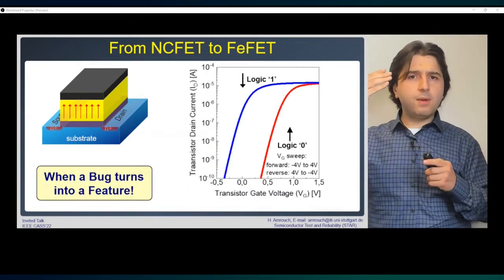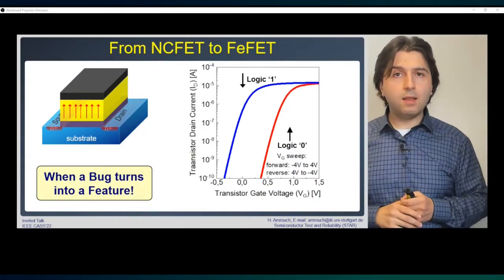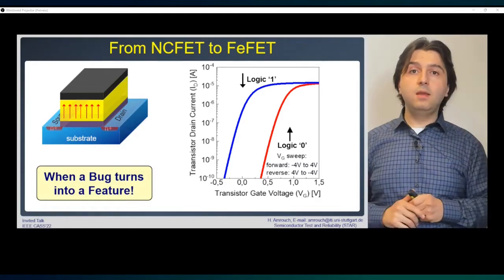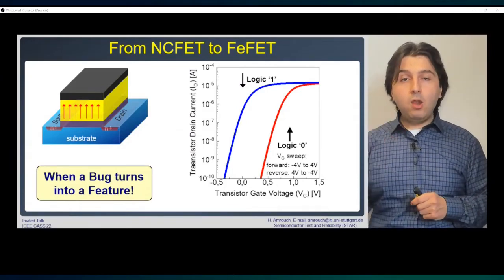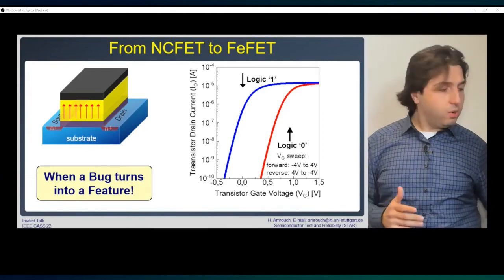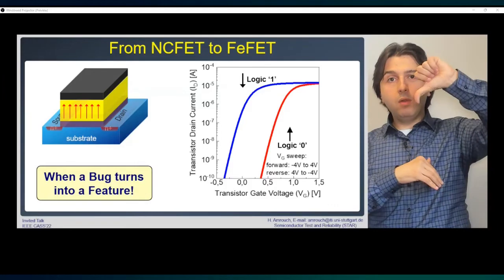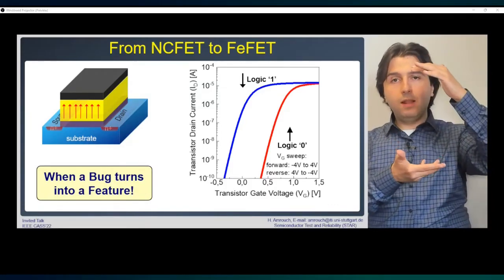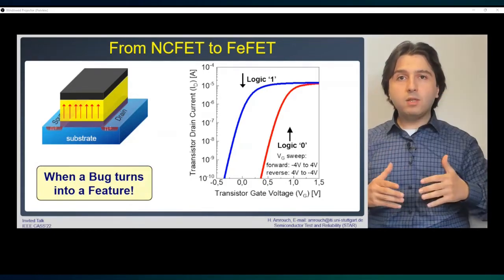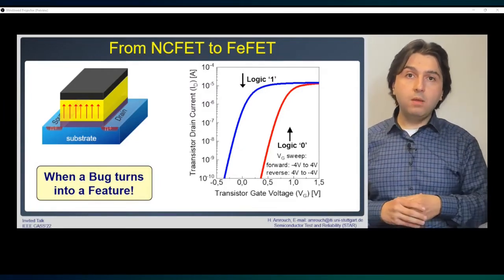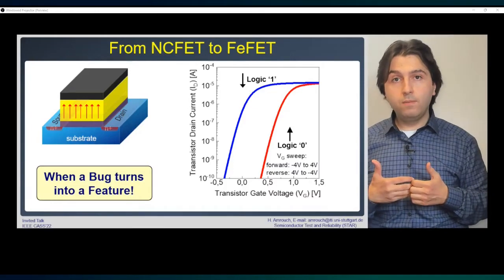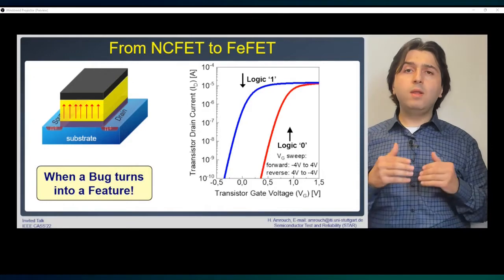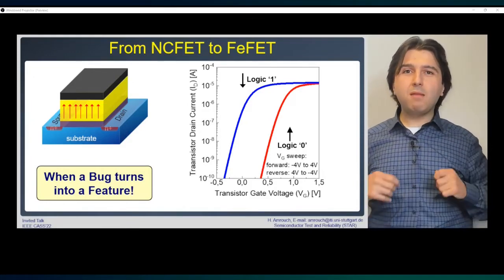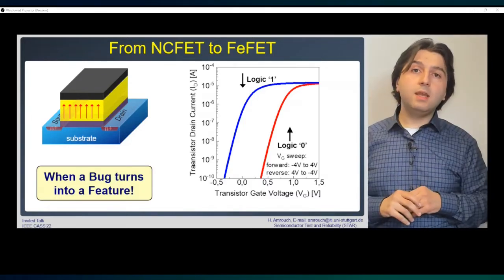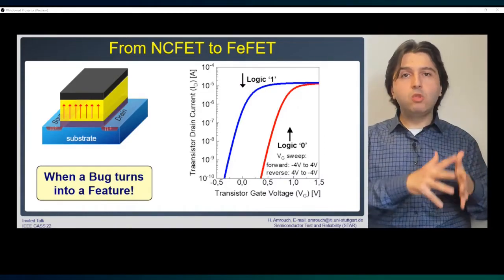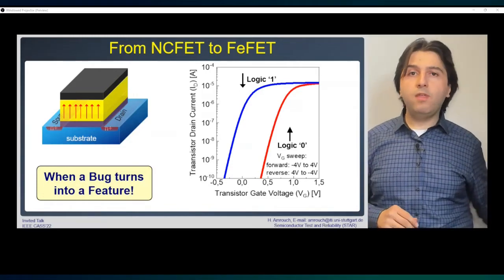But what that really means in practice is that we are able to change the electrical characteristic of the transistor into two different separated states, a low VT state and a high VT state. A high current and a low current. Why? Because when the ferroelectric layer is polarized either up or down, it will now interfere when we apply our voltage and our electric field to turn the transistor on or off. Either it will help and enhance the channel formation, therefore we will get a reduction in the threshold voltage, represented here in the blue curve, or it will actually oppose the channel formation and make it more difficult to turn on the transistor, which is a high VT state because we need a much higher voltage to turn on the transistor, and this is represented in this figure with the red curve.